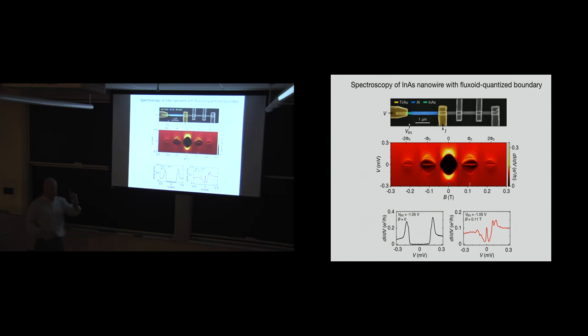You go to the first lobe, where there's a vortex. You've made the vortex yourself in the first lobe, and lo and behold, there's one zero energy state that survives. There's a lot of other states that live also in and around this vortex. These are the so-called Caroli-de Gennes-Matricon states that people find around vortices. But the distinctive feature of an odd number of windings, and we have it also in 3 and 5, is one zero energy mode that lives inside of the system. There it is at the red cut.